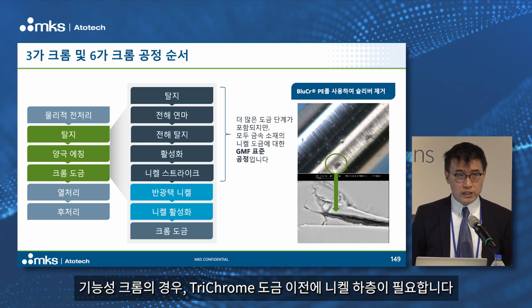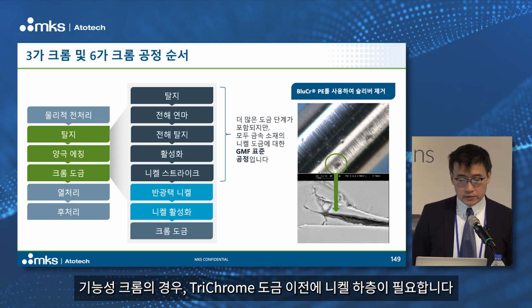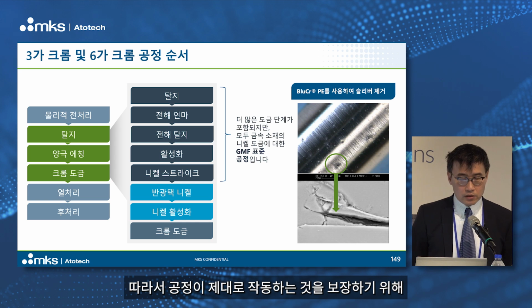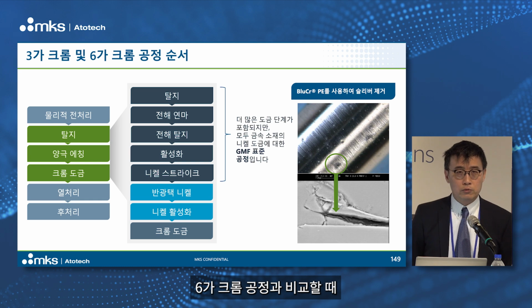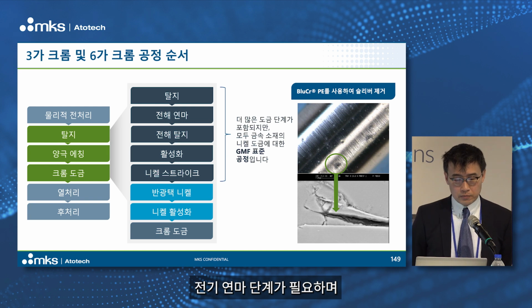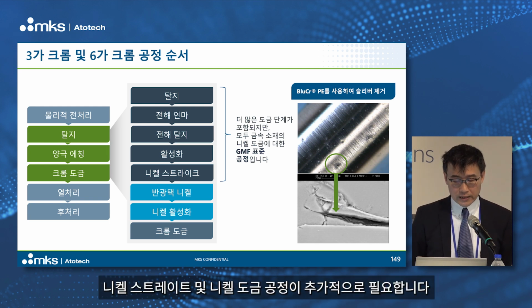For functional Chrome, we need a nickel underlayer before the TriChrome plating. To really ensure that the process is working well, comparable to the Chrome 6 application, we need an electropolish step, and we also need a nickel strike and nickel plating process afterwards.